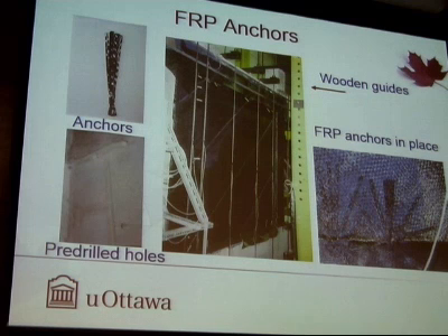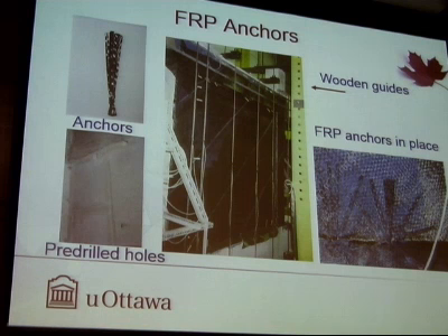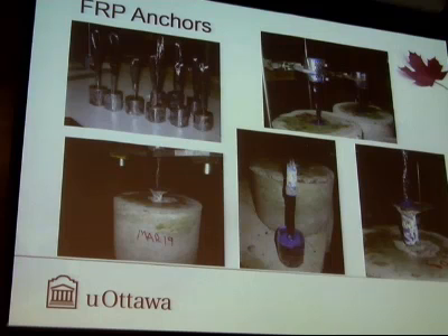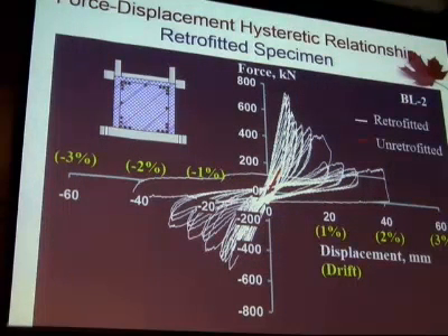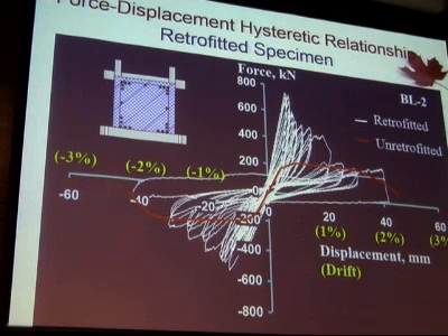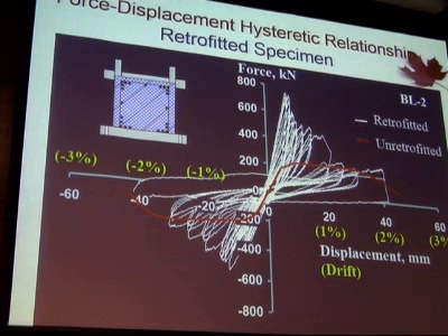Here you see FRP anchors, which are essentially twisted anchors cut from FRP sheets and then inserted into holes, and that then provides continuity between surface-bonded FRP and the enclosing frame elements. Of course, we had to do a special separate study on FRP anchors and came up with a design methodology considering inclination of these anchors as well. Now here you see comparison of unretrofitted and retrofitted specimens, and using FRP did improve strength quite a bit, but obviously we were not expecting too much ductility because you're combining brittle material like URM with brittle material like FRP. So the retrofit strategy for this kind of application is bound to be for elastic strengthening rather than inelastic deformability.